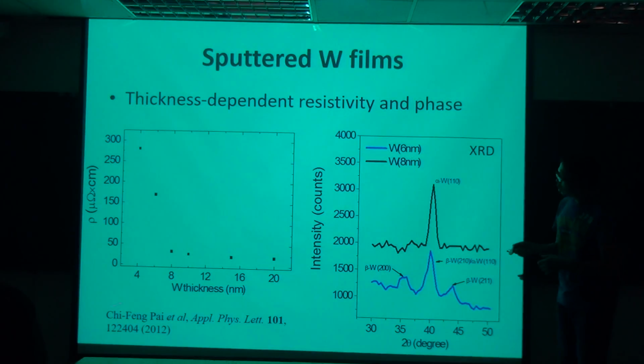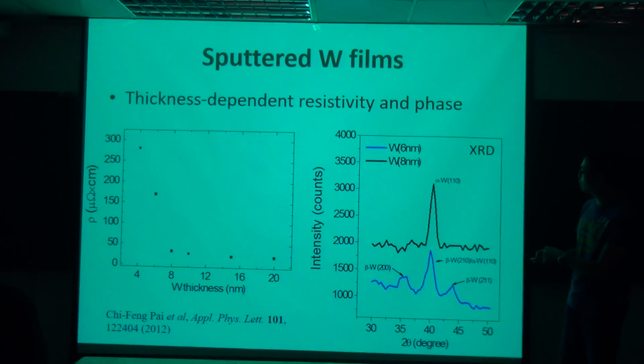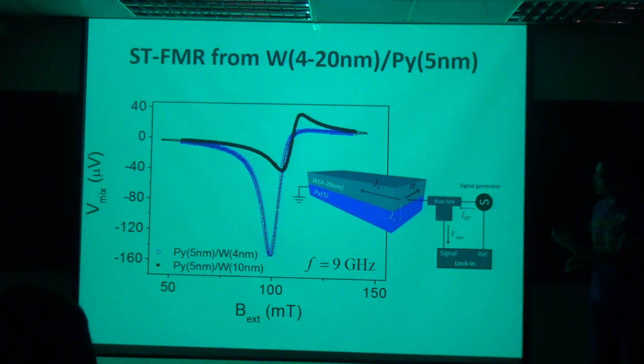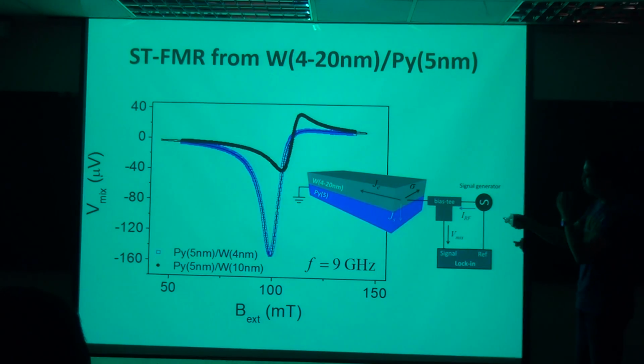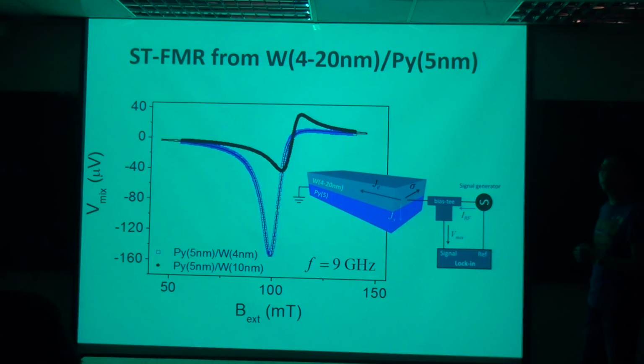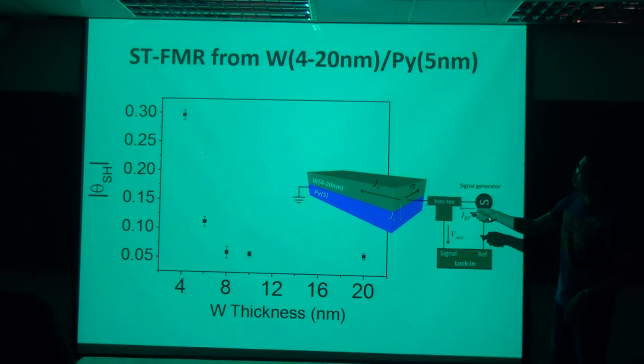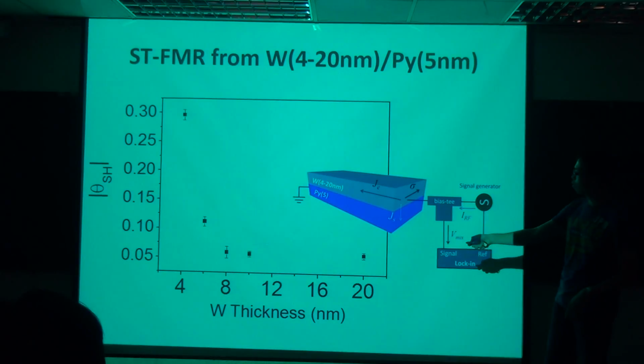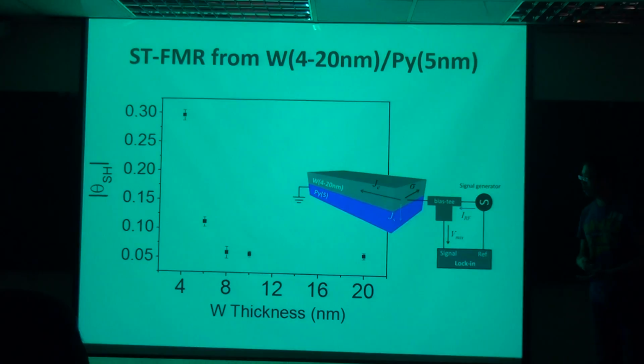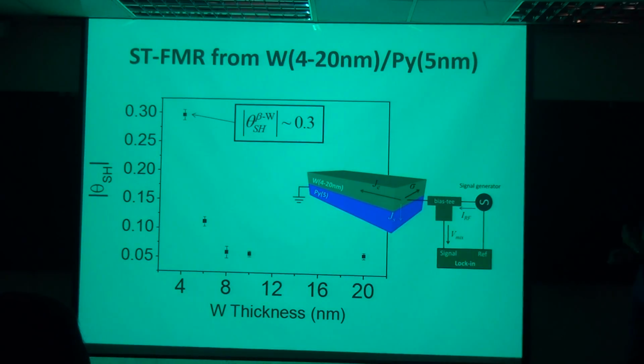And for our sputtered film, like I just mentioned, if you sputter a thicker film, you'll get lower resistance. And we can verify that through X-ray diffraction. And more importantly, this spin-Hall effect will be phase dependent. So if you work on alpha tungsten or thicker tungsten film, you'll see that there's no symmetric component, which means that the spin-Hall effect is small. And if you work on beta tungsten films or thinner tungsten films, you'll start to see a larger symmetric peak, which means that the spin-Hall angle is larger. And if you plot the efficiency or the spin-Hall angle against thickness, you'll also see this drop. So if you go to thicker films, the alpha phase, the efficiency will drop, which means that the beta tungsten is a much better spin-Hall material.